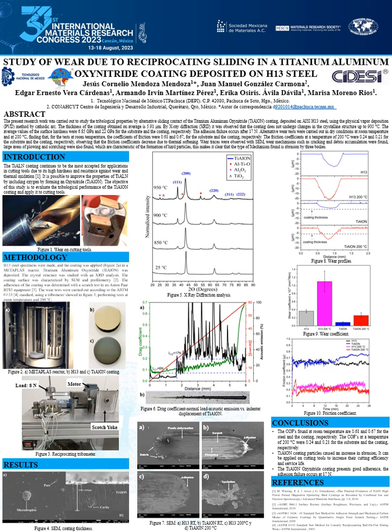Figure 10 shows the coefficients of friction from the reciprocating sliding test. In tests at room temperature, the coefficients range from 0.6 to 0.7. However, in tests at a temperature of 200 degrees Celsius, the coefficients of friction decrease to values of approximately 0.2. This is due to the thermal softening of the materials.